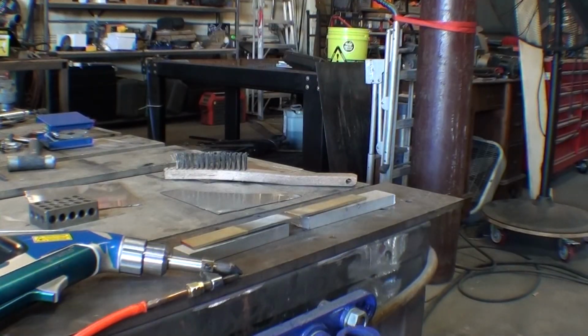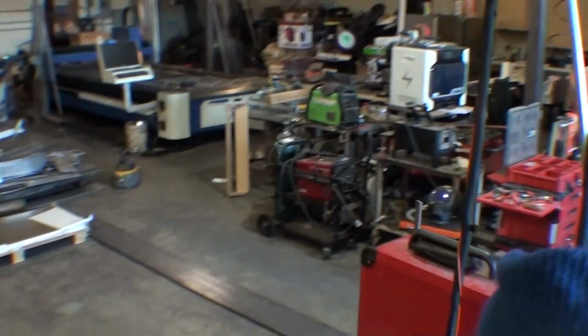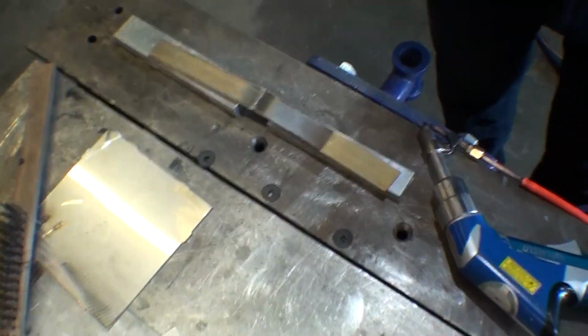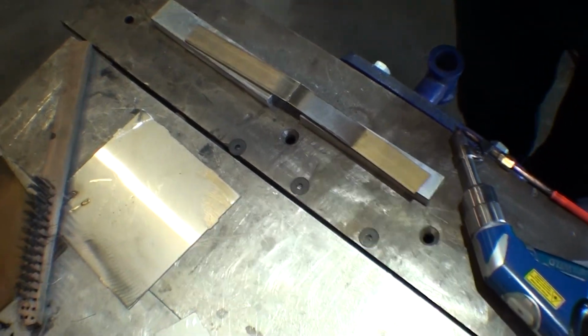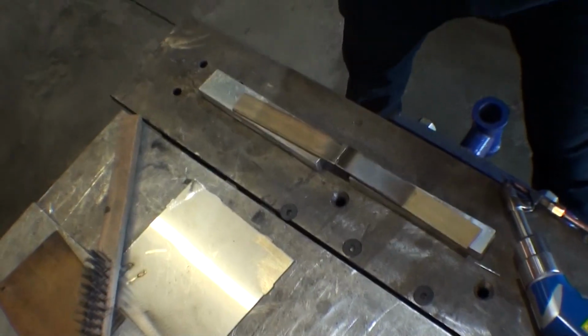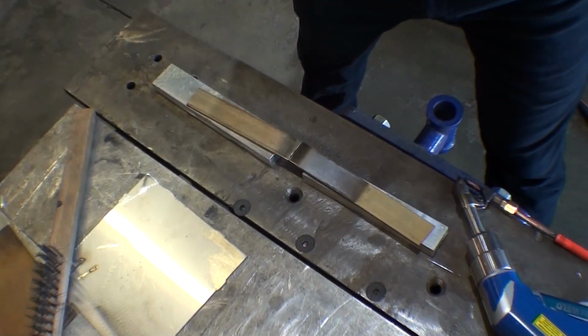Laser brazing with silicon bronze on brass results in surface wetting, not fusion. The laser energy melts the filler, but the brass base stays solid, no metallurgical continuity. The result is a cosmetic overlay, not a structural joint. Silicon bronze melts and flows, but unless the base metal also melts, there's no fusion.